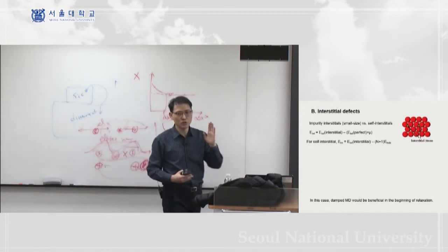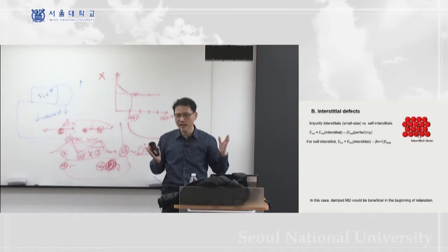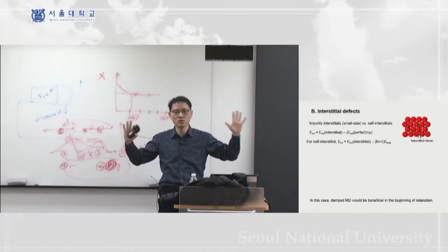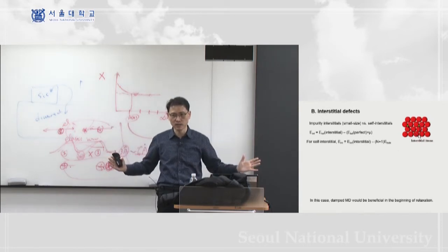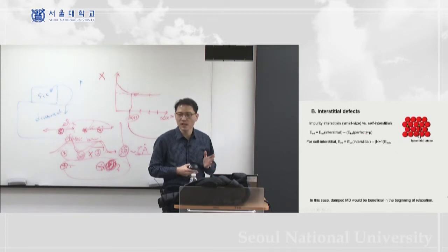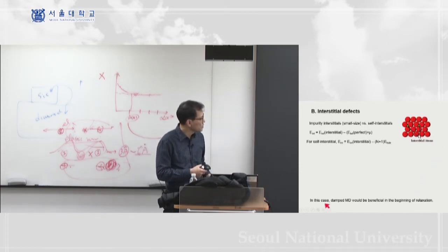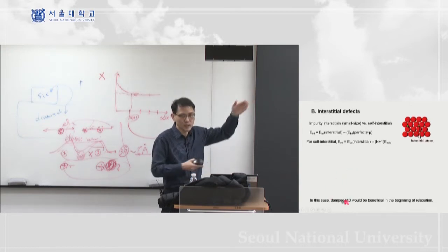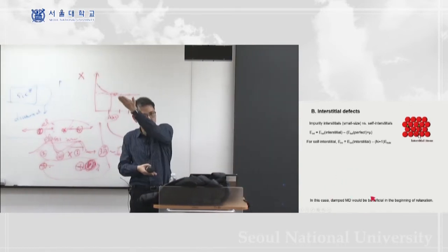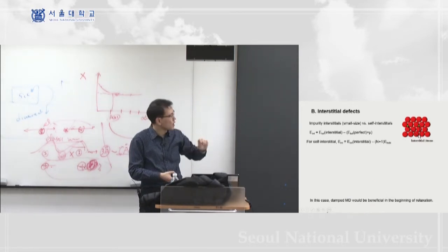In most cases, your guess is wrong, and you put the atoms in a quite crowded area. It causes lots of atomic force, or stress, on the atoms around the defect site, which means the atoms around your initial starting point will have extremely large force. So you are quite far from the equilibrium state on the energy surface.